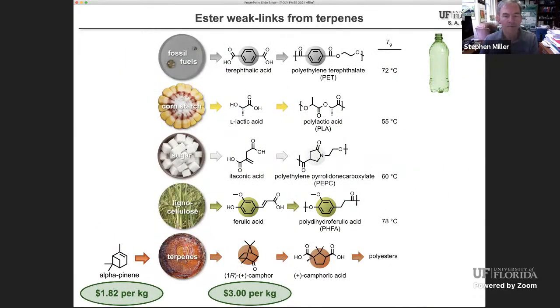So we've also moved on to another class of bio-based molecules, terpenes. A lot of people work on these as starting materials for making a variety of polymers. So alpha pinene is a fairly inexpensive terpene. There's a pretty large demand, surprisingly, for camphor. So rather than extracting it from camphor trees, there is now a synthetic protocol that takes alpha pinene, which is far more abundant and available in tree sap and pine trees. You can convert alpha pinene to camphor. And because of this commercial demand, camphor itself is a fairly inexpensive commodity at about $3 per kilogram. Okay, so maybe less than $1.50 per pound.